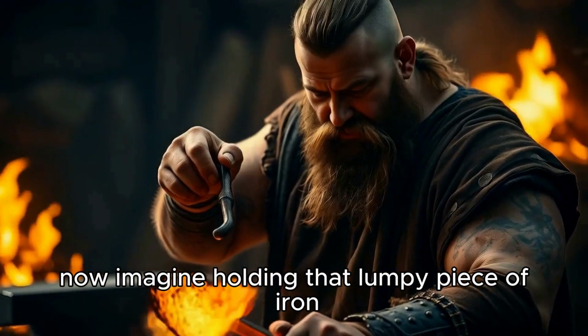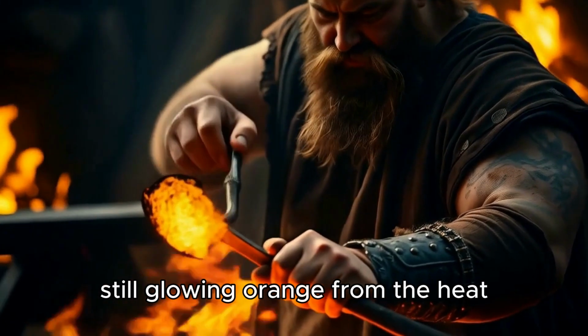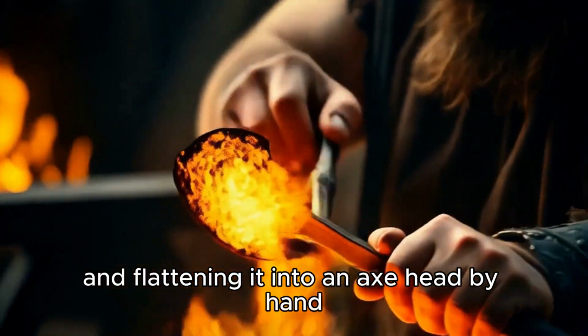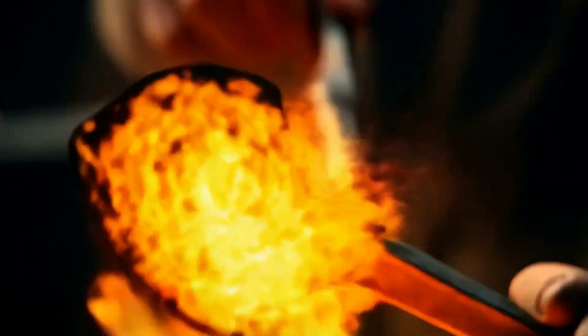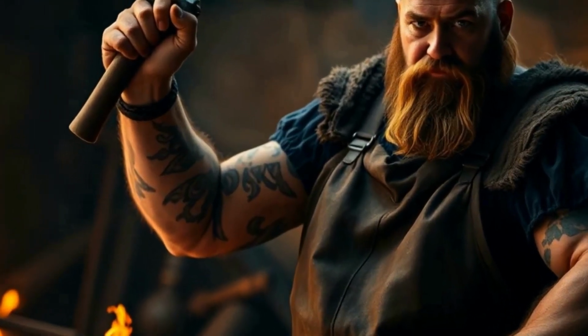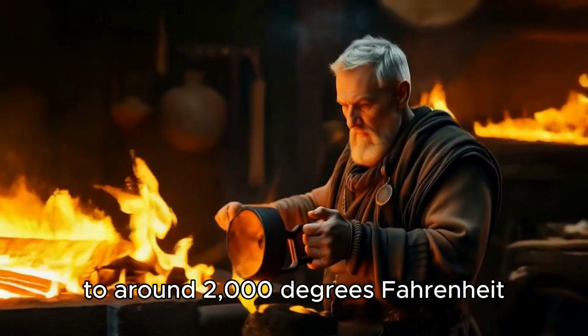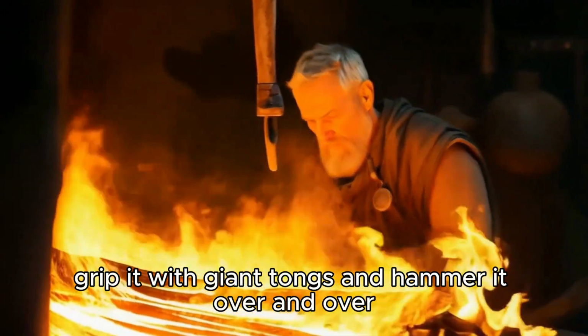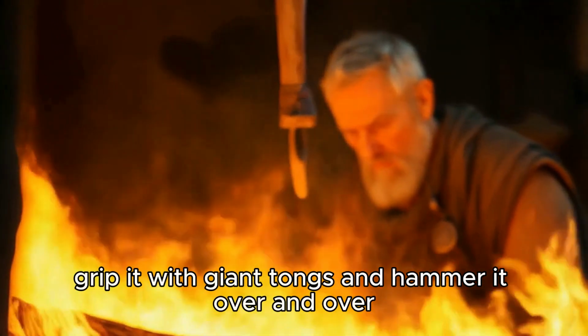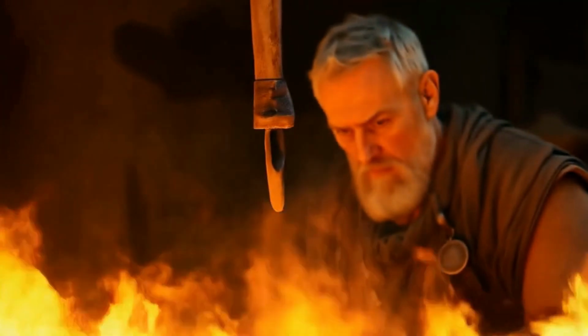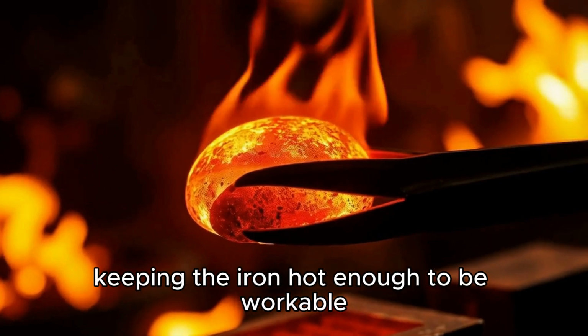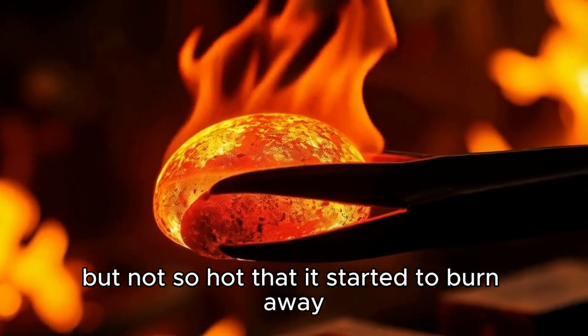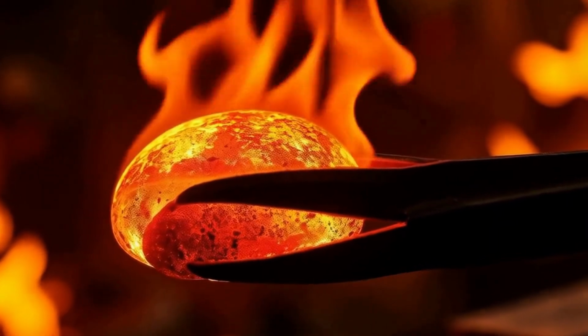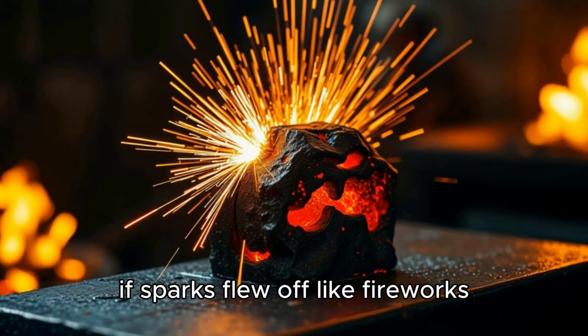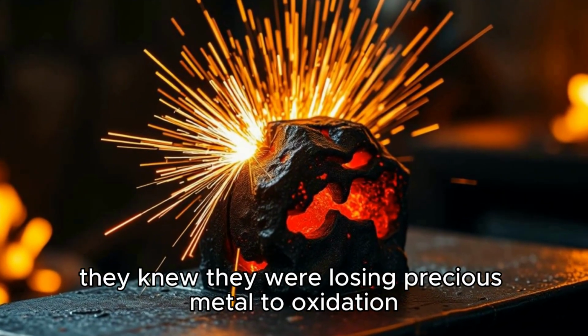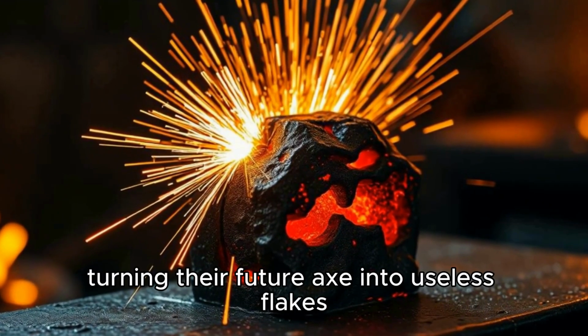Now imagine holding that lumpy piece of iron, still glowing orange from the heat, and flattening it into an axe head by hand. That's what came next. They'd reheat the bloom to around 2,000 degrees Fahrenheit, grip it with giant tongs, and hammer it over and over to stretch the metal into a rough blade shape. The trick was keeping the iron hot enough to be workable, but not so hot that it started to burn away. If sparks flew off like fireworks, they knew they were losing precious metal to oxidation, turning their future axe into useless flakes.